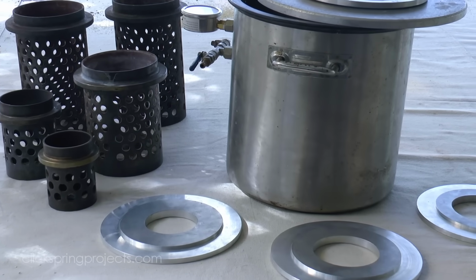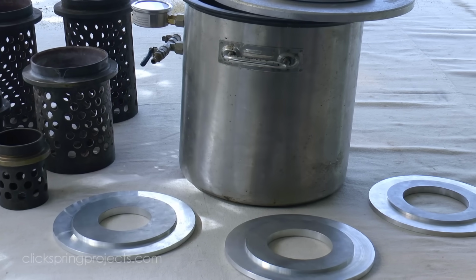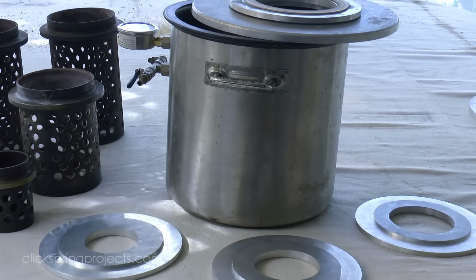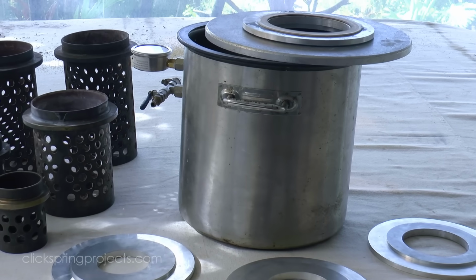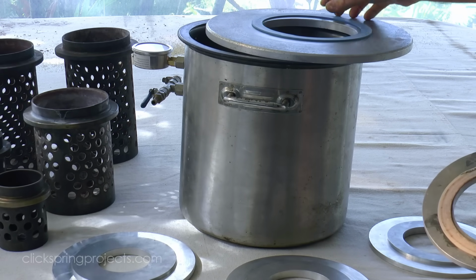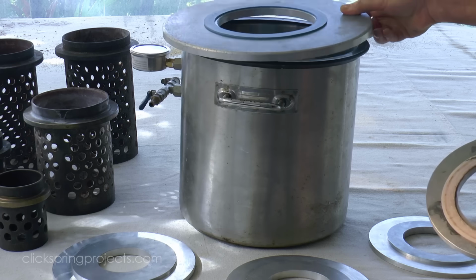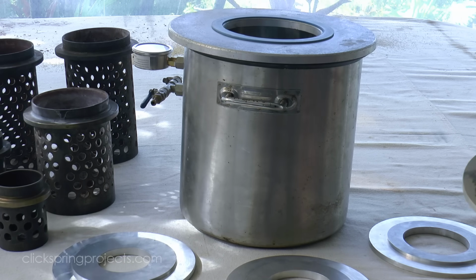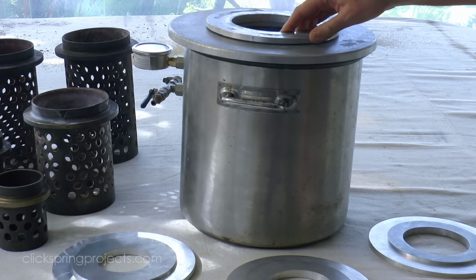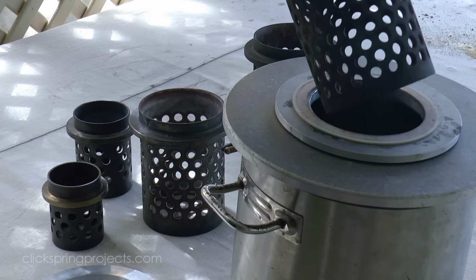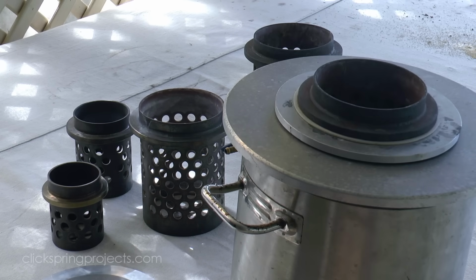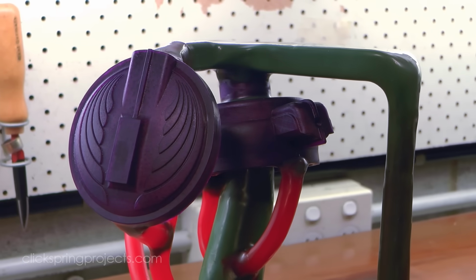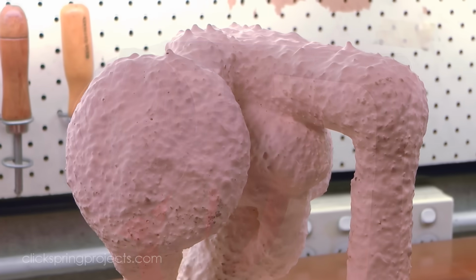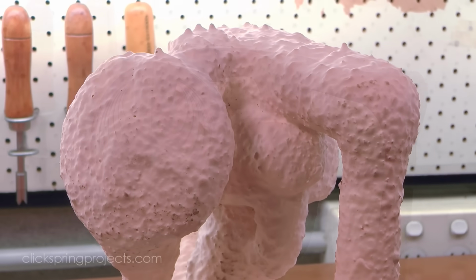In the previous TGT episode, I described a compact and versatile vacuum system suitable for working with typical gypsum-based investment when lost wax casting. Gypsum investment is quite easy to remove from a finished casting, and that characteristic often makes it the preferred investment if all other aspects of the casting outcome have been satisfied. But if the nature of the part to be cast is such that greater strength of the investment is required, or if higher metal temperatures must be endured, then the ceramic shell process may be worth considering.